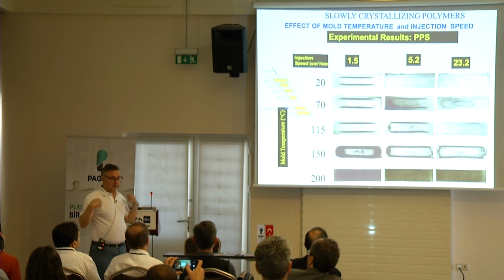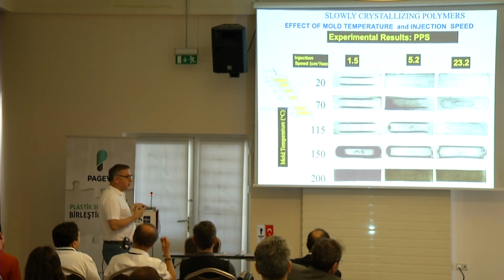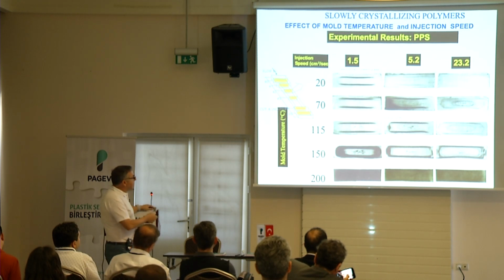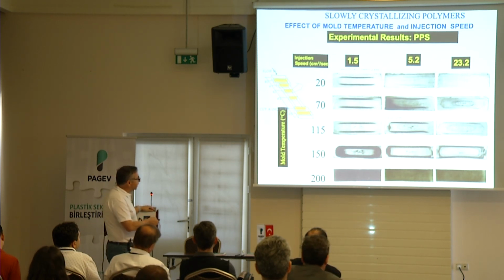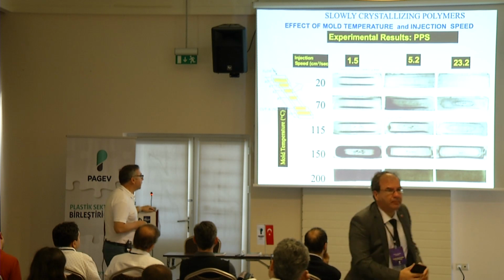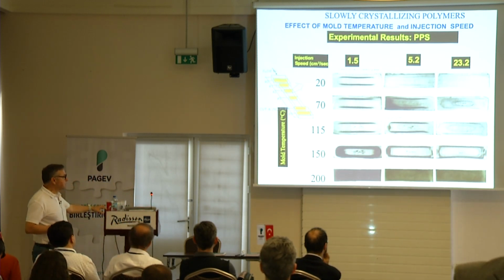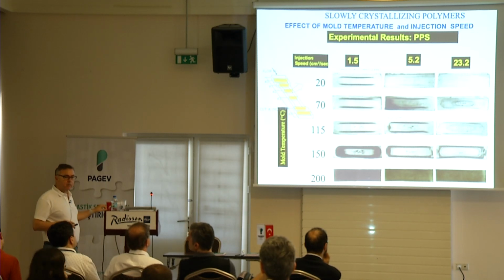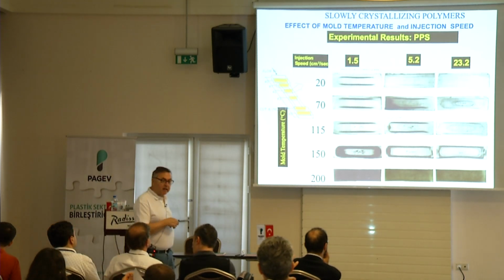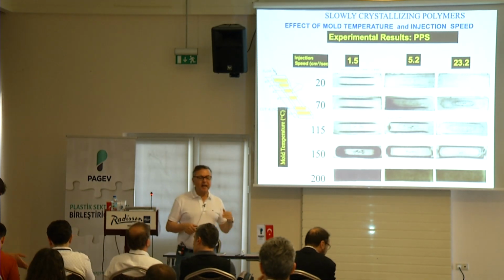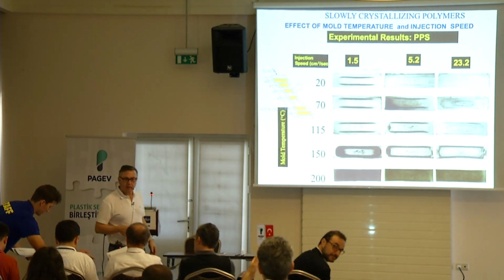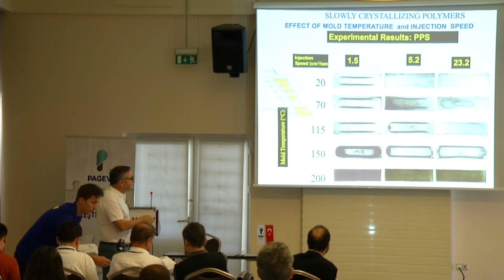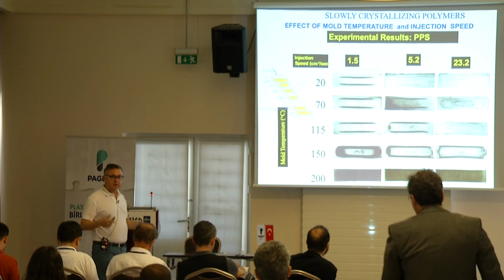Counterintuitive. The higher the injection speed, well, we do influence the shear layer formation. If I go to higher temperatures, it gets darker and darker. And remember, the Tg is here, the glass transition temperature. Above that, essentially the material becomes homogeneous, dark. Dark means it's crystallized, not completely, but to a certain extent. But the bright means it's amorphous.